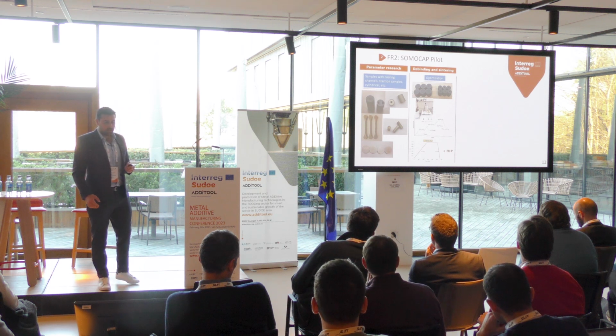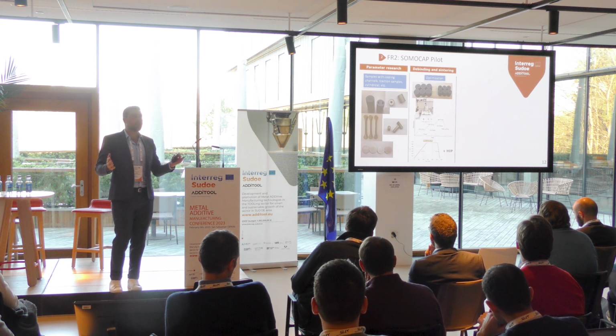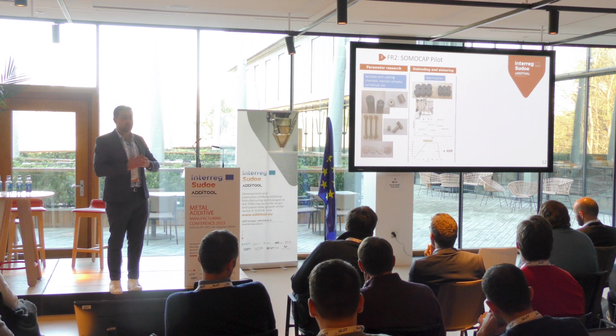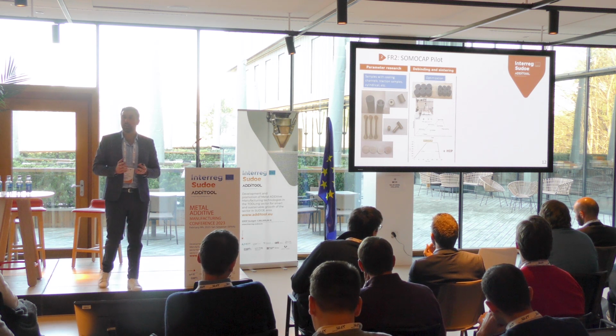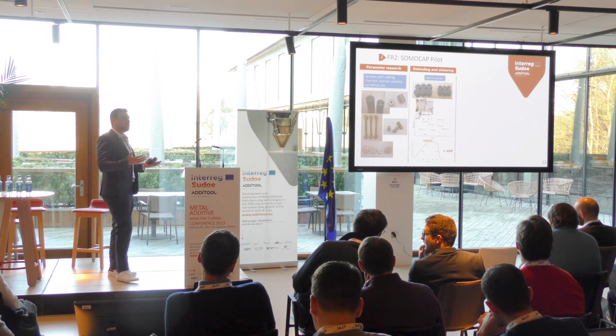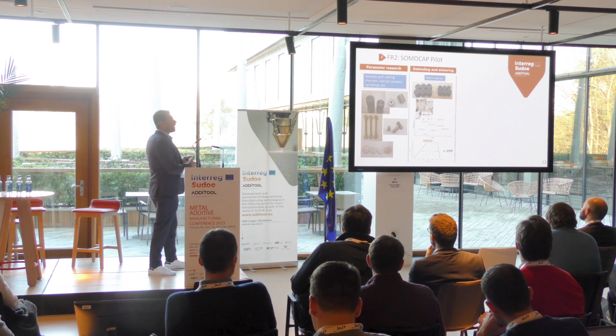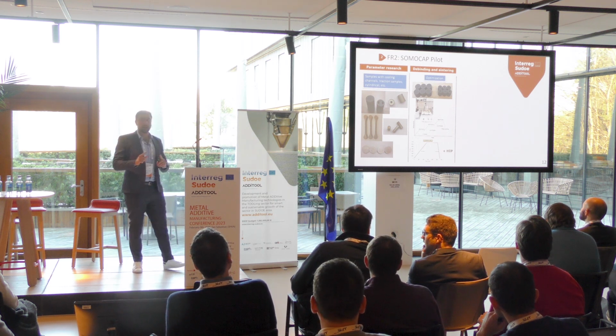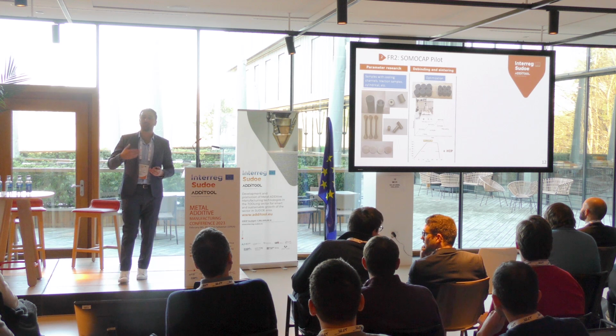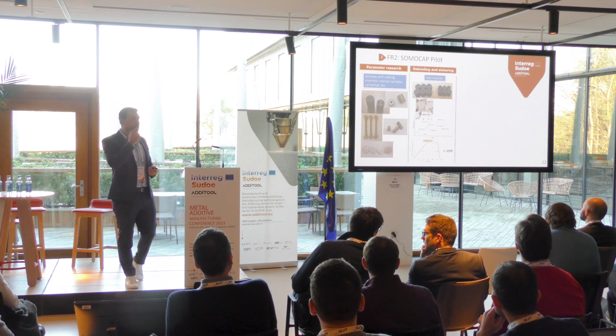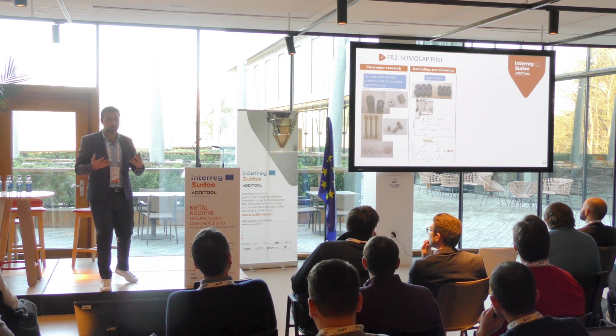Then this is the main critical aspect: the debinding and the sintering. The printing is quite easy, but to debind and sinter is difficult, to debind and sinter well and to have good properties directly on the material. And we have to control it.